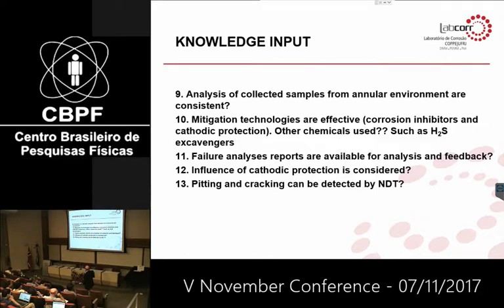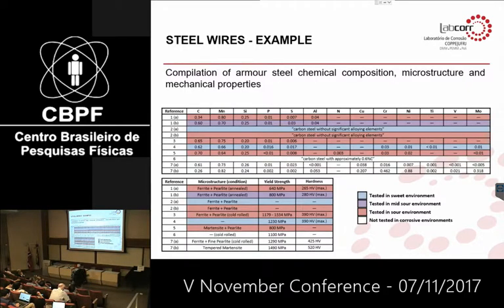The failure analysis reports are very important for feedback. Influence of cathodic protection is considered, and the possible detection of localized corrosion. This is an example of a compilation of different papers in the literature done by one of our students, a student that has now moved to Oslo. And we can see that we can identify different materials, all of them carbon steels, but with different compositions, different microstructures. And most interesting, tested using different approaches.